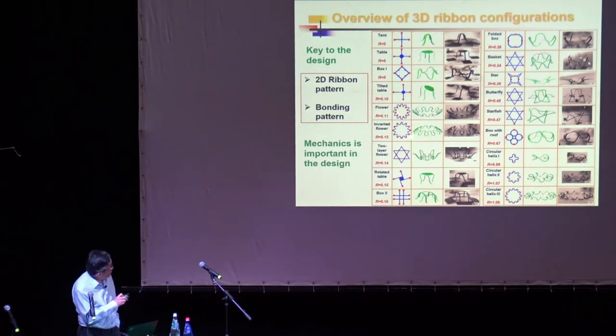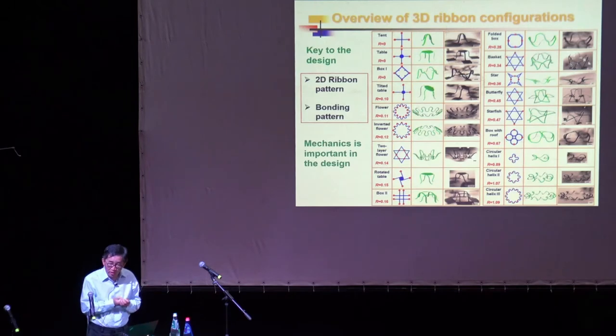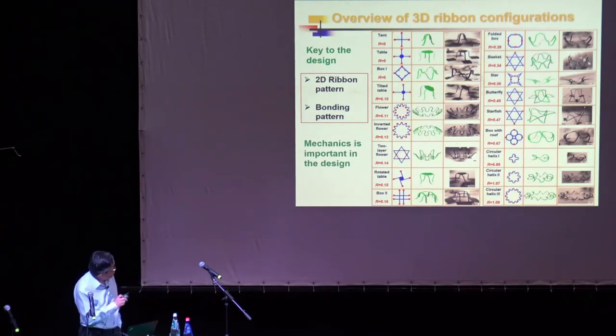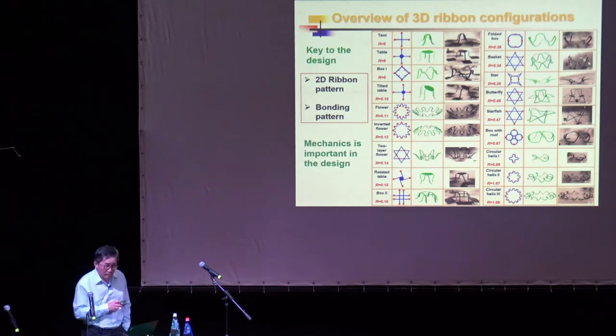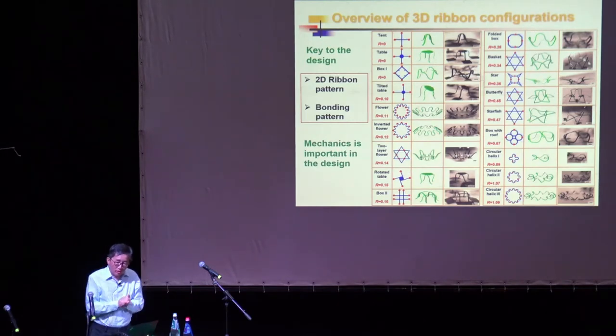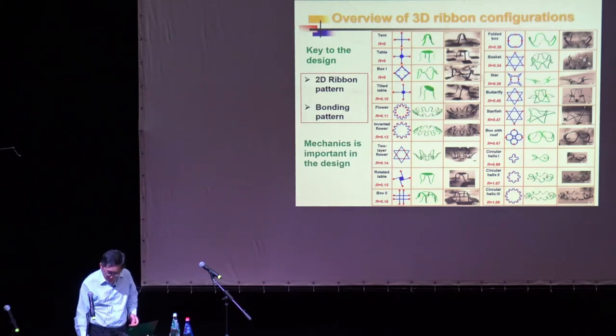However, the material's deformation is large. So total deformation is still nonlinear, fitting for this nonlinear mechanics conference. So it's really small, linear elastic behavior, but nonlinear finite deformation. The second reason for the theory to agree so well with experiment is that we can do mechanics computation of post-buckling very precisely now. So we really don't need parameter fitting, and the theory and experiment can agree so well.